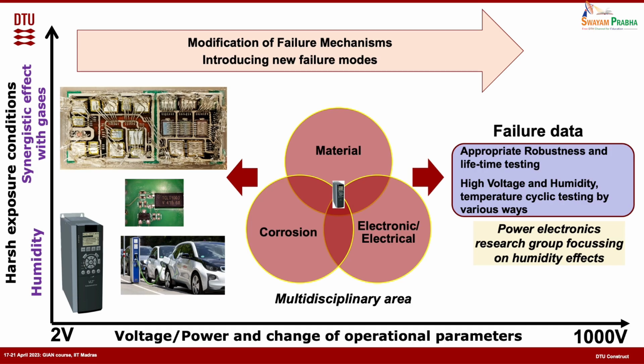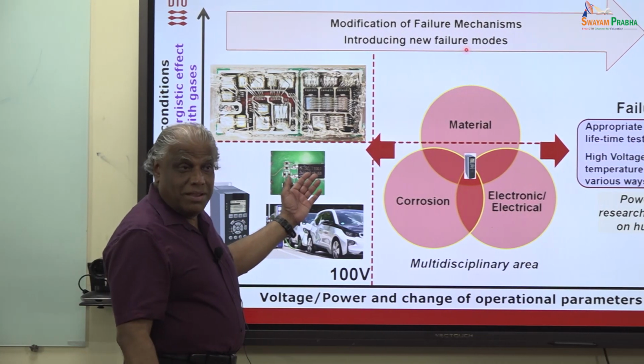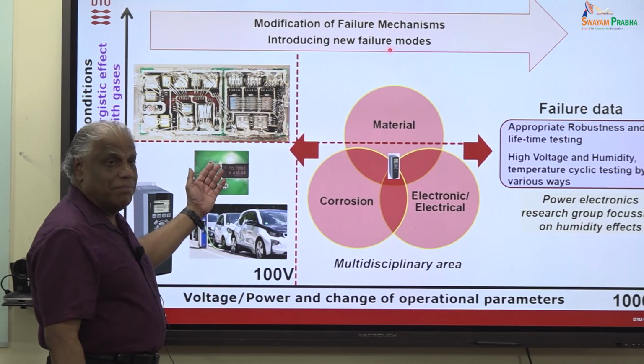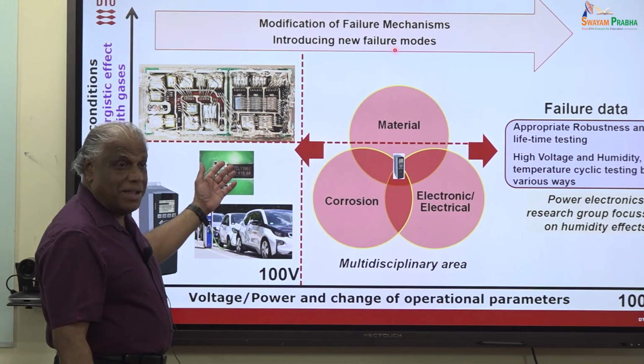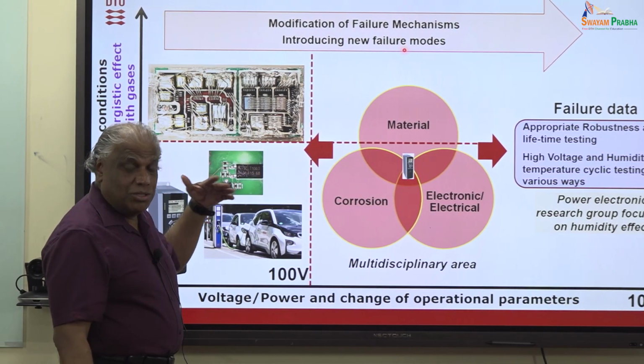So you cannot pass more current. So we do the electrochemical modeling, and it also shows that there is a saturation of current. Think about a copper wire of a certain thickness: what happens if you keep increasing the current? At one current level, the copper wire will burn because it is taking more current. In a similar way, you cannot pass the current through the water film above a certain level, and maybe because of the resistance it gets heated up and the water film will evaporate. That's all.